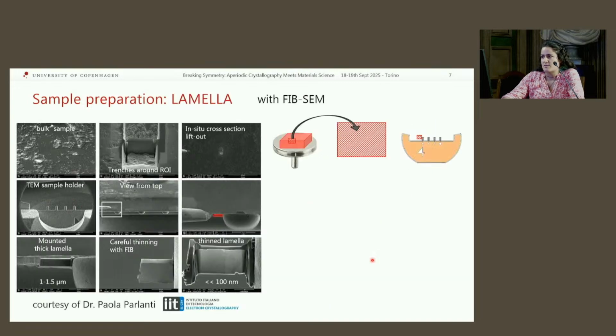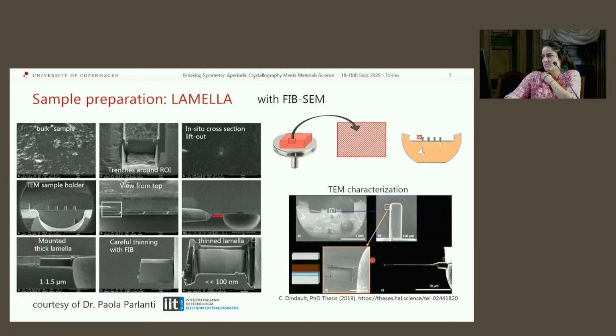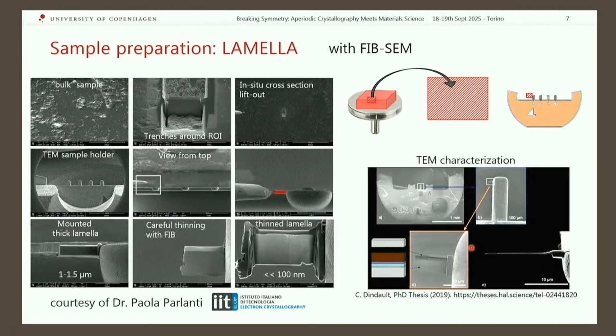But we have seen in some cases we have a bulk sample, for example, the rocks, the meteorites, and so on. So in this case, we need to find the region of interest of our bulk sample, and then we can use a focused ion beam to very precisely cut a cross-section of this sample to have a very thin lamella that we can analyze with transmission electron microscopy. So you can see here, it's a prepared lamella from a multi-layer sample, and after the preparation you can still see the layers, and on the other hand the lamella is very thin, it's tens of nanometers.